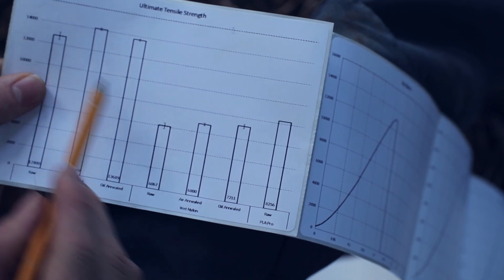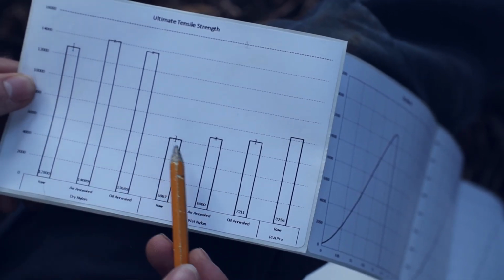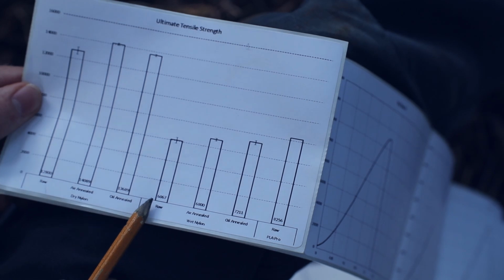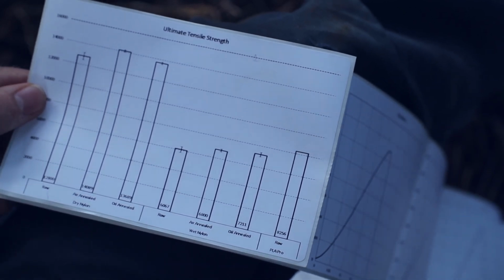So over here, you can see the raw nylon saw a massive drop in tensile strength. It dropped to less than half its tensile strength. It's ridiculously weak now. It's down to around 6,000 pounds per square inch, which is really weak. That's at the level of ABS or PETG. That's not good. That's quite weak.